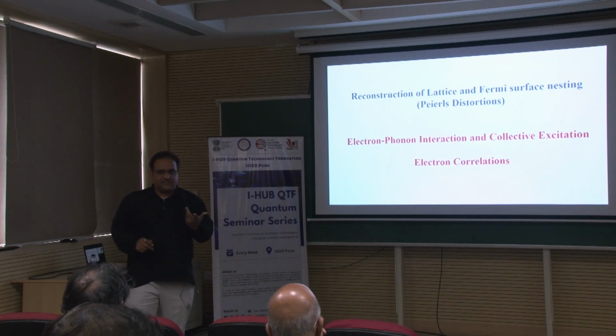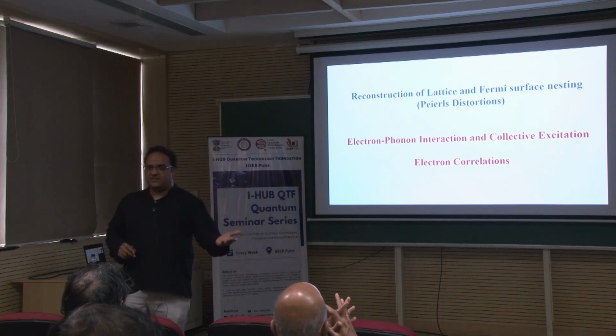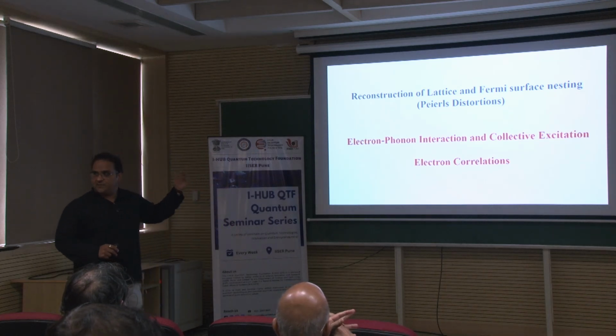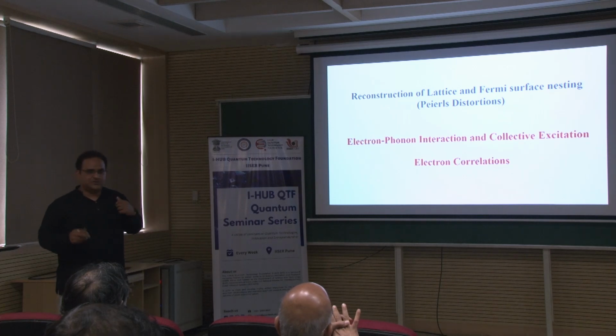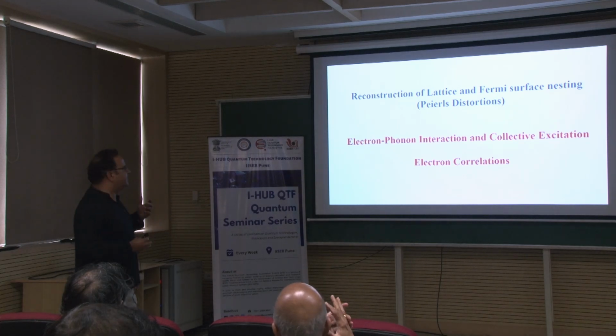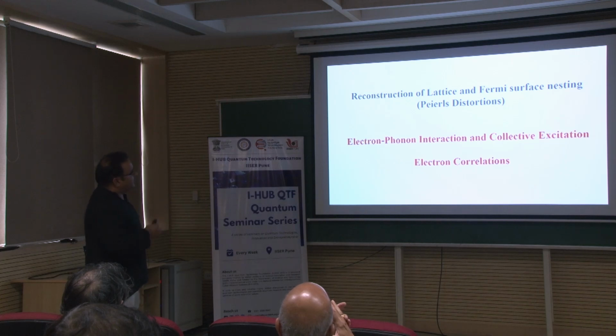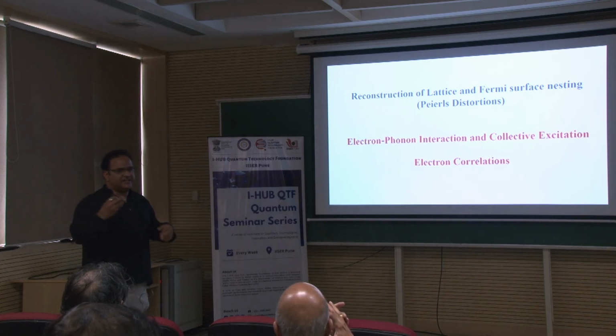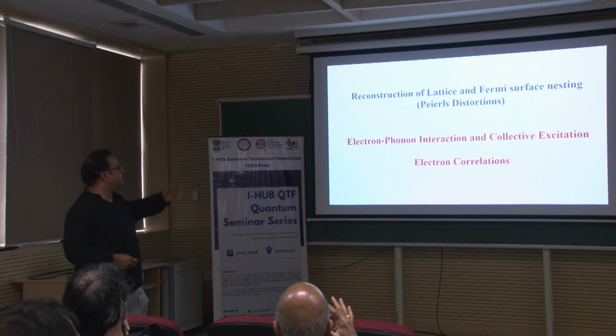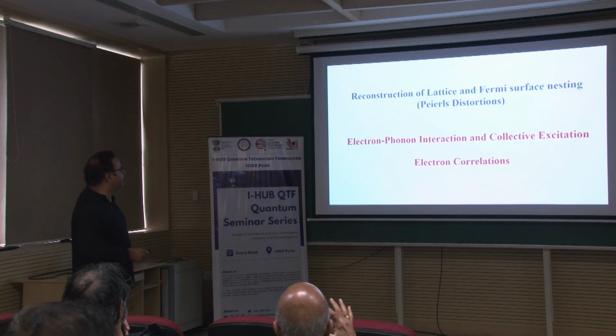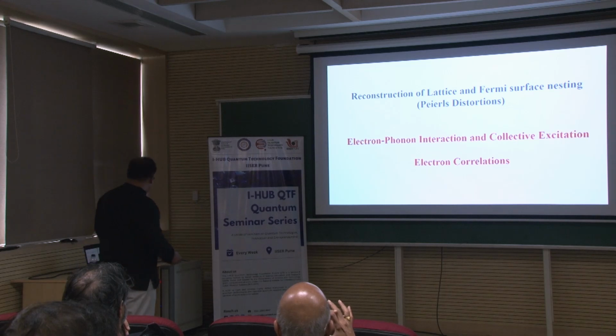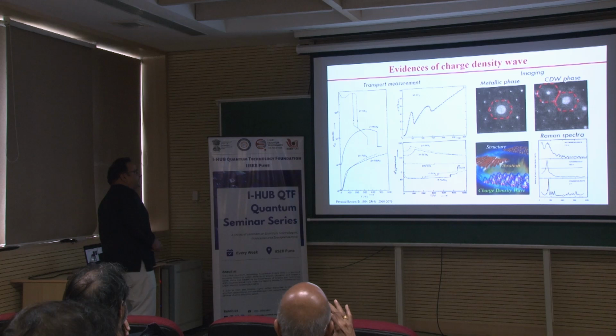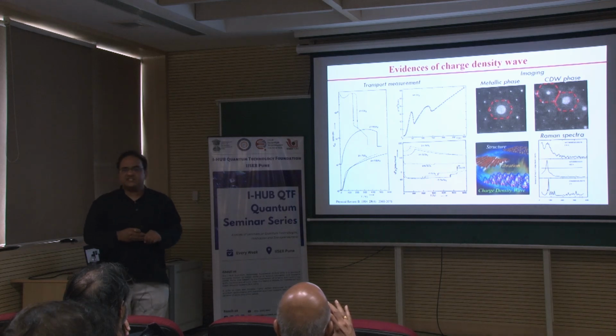Now, the discussion is whether the Fermi surface nesting is the reason for the charge density wave or the electron-phonon coupling is the reason for the charge density wave. Different materials will show a different origin for the charge density wave. For example, if you have a metallic system, you say that it is more the Peierls distortion or the reconstruction of the lattice, but most of the chalcogenide materials show that the charge density wave is driven by electron-phonon interactions. Now, what are the evidences of the charge density wave?